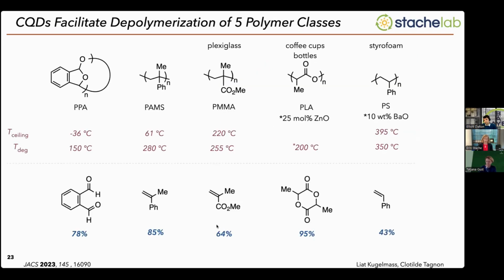Now, notably, this depolymerization strategy works across an entire breadth of polymer classes. It's not restricted to just vinyl monomers. It can work for anything that will thermally depolymerize because it's just generating heat. And so polyphthalaldehyde, which was initially used as a photoresist, depolymerizes very easily under our reaction conditions and gives high monomer yields. Alpha-methylstyrene, and commercial polymers like polymethyl methacrylate, or Plexiglas, which you're all probably very familiar with, depolymerize very well to generate methyl